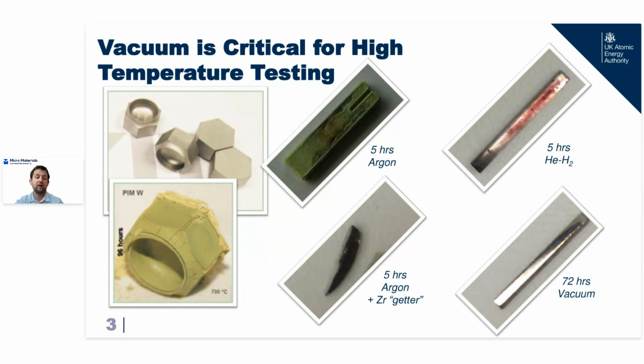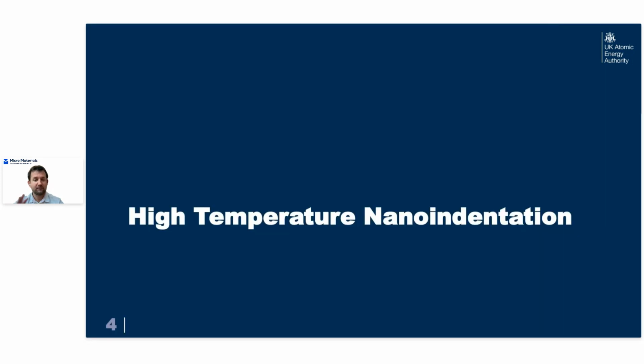It completely destroys them. And so we found very early that it's absolutely vital to test in vacuum when we go to these very high temperatures, where you can see that we have this pristine sample here on the right for these sorts of temperatures and these sorts of reactive metals. So everything you see here will have been done in vacuum. And what I'll show now is the work that we did trying to get our system up to hit that 1,000 degree nice round number milestone.